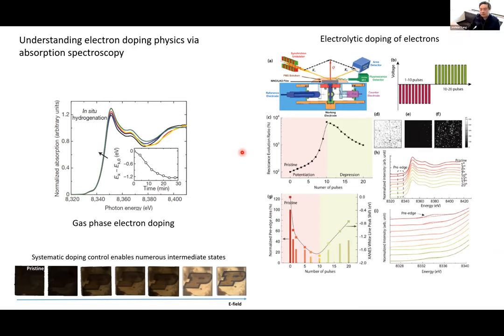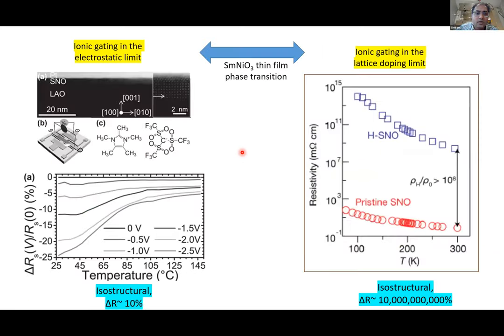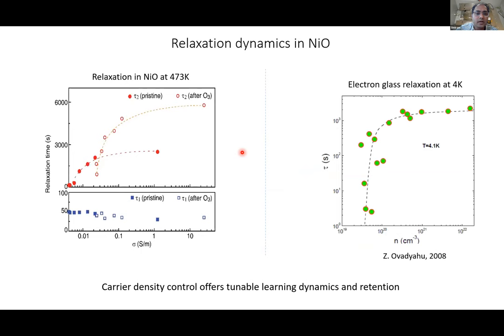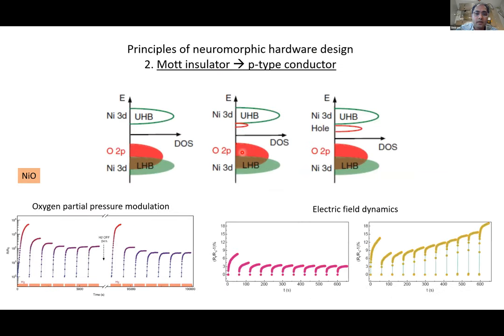Another quick question is similar. You have shown nickel oxide and nickelates. They have similar properties. What's the advantage of using those perovskite nickelates? In the nickel oxide, everything is through oxygen vacancies. Everything I showed here in the nickel oxide is basically hole doping through oxygen interstitials, and then removing them through hydrogen annealing.